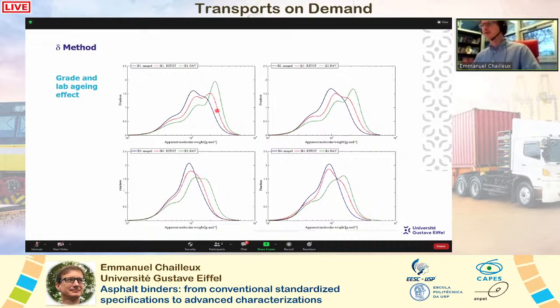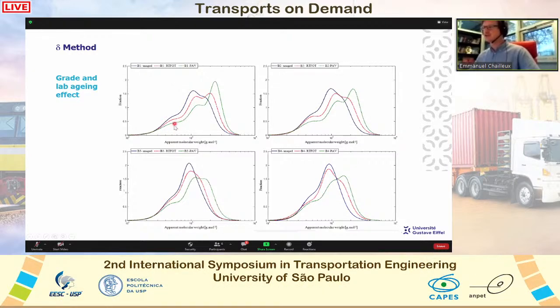So if we look at the effect of lab aging on grade, we see that we can distinguish between grade and aging also. So here we have a very soft binder, and here a very hard binder. And we recognize that the lab aging leads once more to an increase of the highest population, and the lowest population decreases in percentage. So we use this lowest molecule to increase the highest molecule by molecular association. So chemical or physical association.